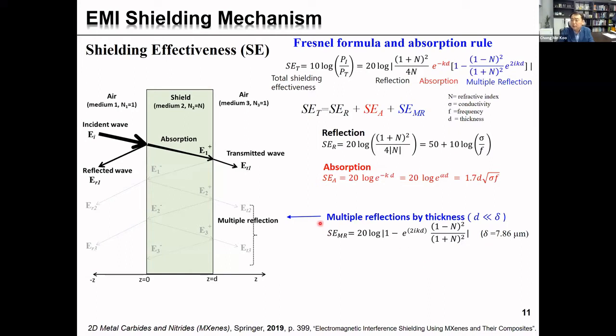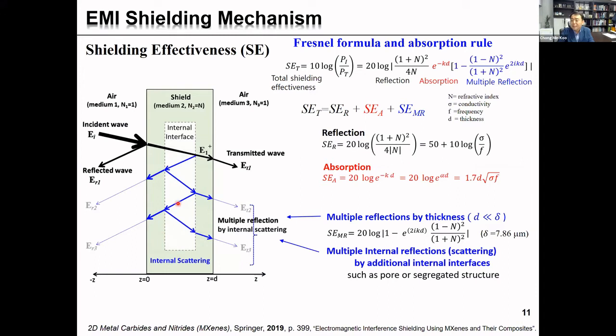Multiple reflection also affects the shielding effectiveness. The multiple reflection can be caused by the thin film effect, when the thickness is thinner than the skin depth. And multiple reflection can also be caused by the internal interfaces of porous or segregated structures. Multiple reflection by internal interfaces significantly improves absorption and shielding efficiency due to the improved internal scattering effect. I will discuss this multiple reflection effect in detail later.